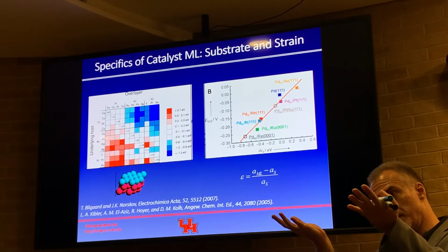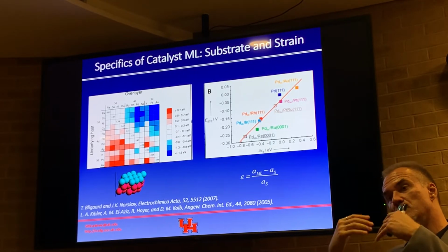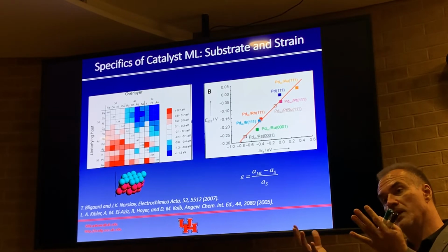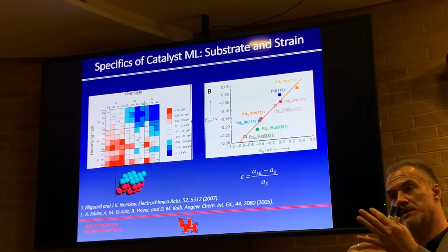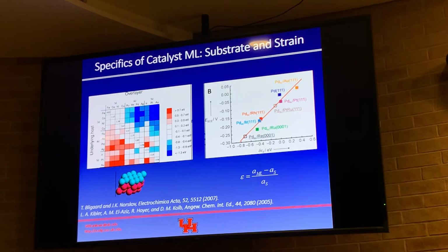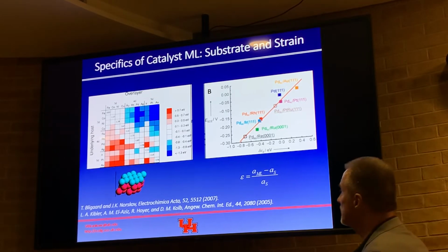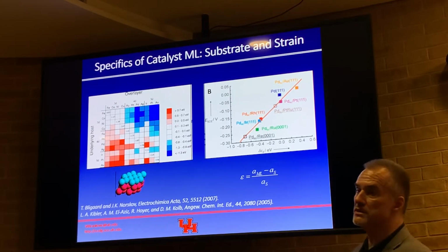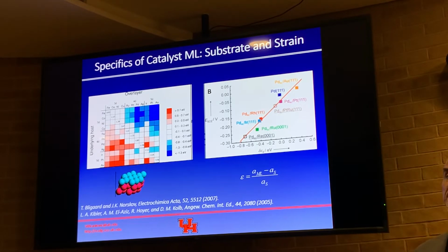because the electron density is pushed up towards the Fermi level, which means more electrons are available for adsorption or reactive overlap with some kind of reactants. Or it could be pushed down, which means less electron density will be on the surface available for catalytic action. Okay, so you get the theory, right?